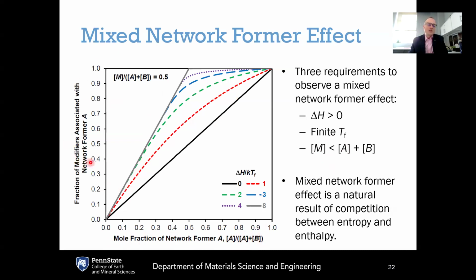And then the y-axis shows the fraction of modifiers associated with network former A. And the different lines here are different delta H over kTFs. So zero here, this black line is if you're completely dominated by entropy. The gray line, where you've got a large delta H over kTF, would be the limit of having an energetically controlled structure. And then everything in between here shows where you have some trade-off between entropic effects and energetic effects. And you can see the nonlinearities that occur for anything that has a trade-off between entropic and enthalpic effects.